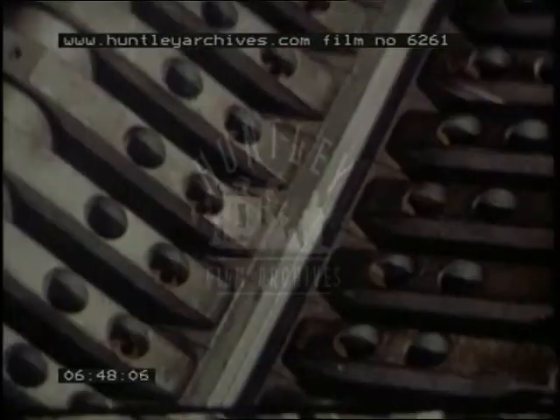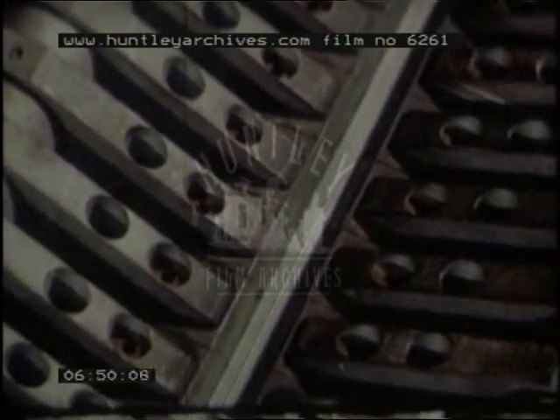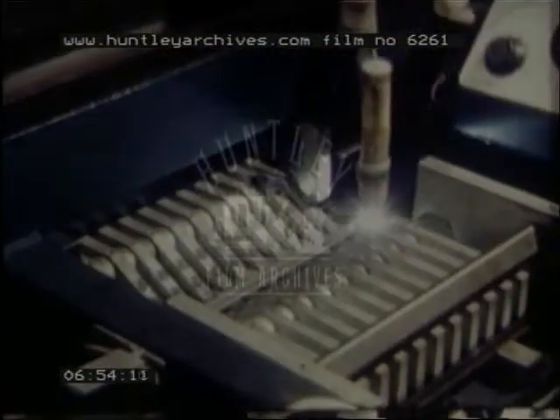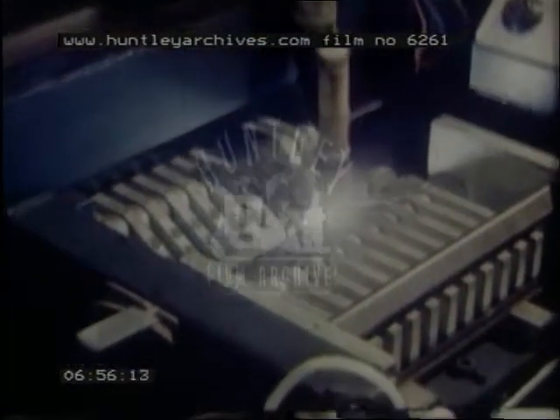The production personnel quickly devised a fixture to ensure precise location of one edge. It is then simple to position the other edge correctly. This automatic setup was not achieved without considerable time and effort, but it is a rapid and economical method of making a joint that needs no further attention. A weld runoff tab is used to avoid any imperfection at the edge of the wrapper.